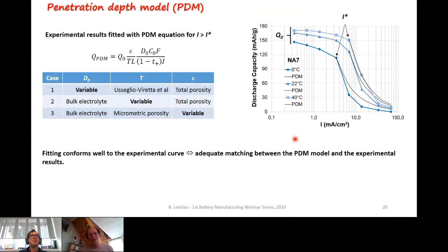So Lestriez has fitted his electrochemical data with this model. Some examples are shown here for the Na7 electrode at the 3 temperatures. You see that the model predicts well the brutal capacity drop for a certain current. The model does not allow predicting the capacity below this current, this I star current, because it only considers the ionic transport limitation. This is also the reason why there is a discrepancy at very high rate, because the model does not take into account the large cell polarization at high rate, which adds some capacity loss.